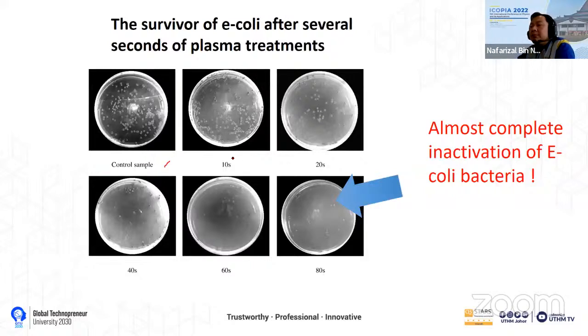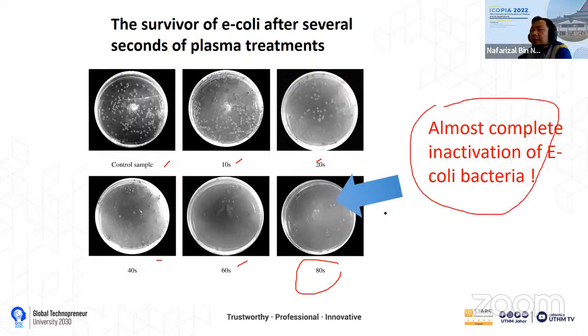The control sample, and then when we expose for 10 seconds, 20 seconds, 40 seconds, 60 seconds, and 80 seconds. We can see that when we expose this to the plasma jet, almost all the E. coli was inactivated, in just about 1 minute, 1.5 minutes.